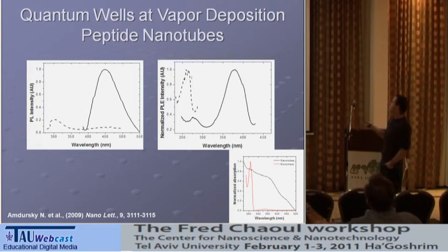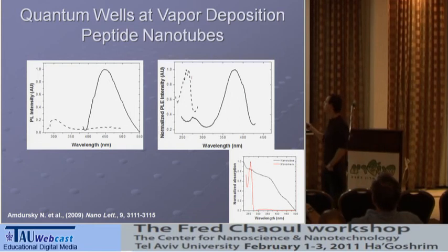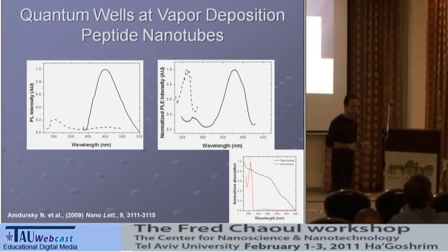And the origin, this is the photoluminescence excitation of this blue luminescence, is coming mainly from the second step, and part of it comes from the first step. This is at the same place as the steps. So we thought to ourselves, we've got new structures which should behave like quantum wells, and we got a new and exciting luminescence, so let's try to see it.